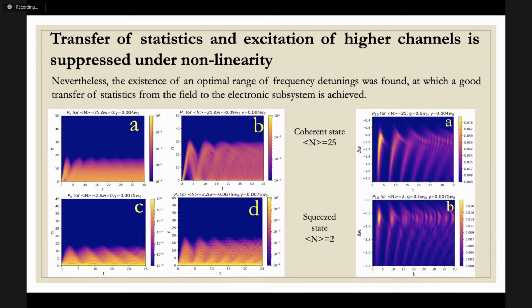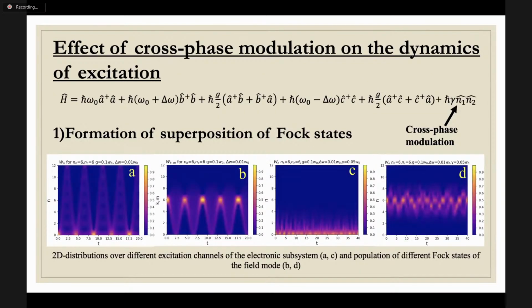So it can be seen that it is really possible to achieve good excitation of the upper channels, but it is mainly achieved at the initial stages of dynamics. Next, we will proceed to the results obtained for the interaction of a nanosystem with two field modes in the presence of the nonlinear cross-phase modulation.